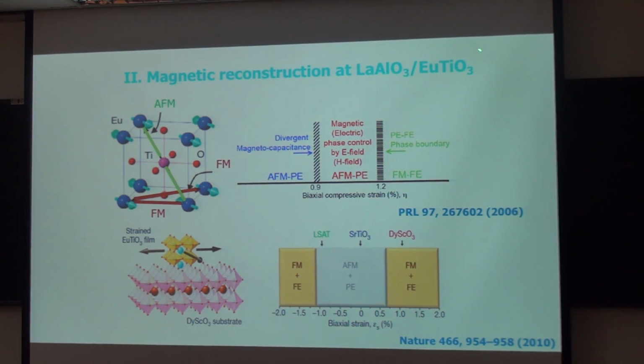Europium titanium oxide has a similar structure to STO as well as SMO. The A site is composed of europium, which has seven localized 4f electrons. And in the bulk form, it is antiferromagnetic and paraelectric. Pioneering theoretical work by Rabe and Spaldin has shown that if there is an epitaxial strain imposed, the system will change from antiferromagnetic paraelectric to ferromagnetic ferroelectric.